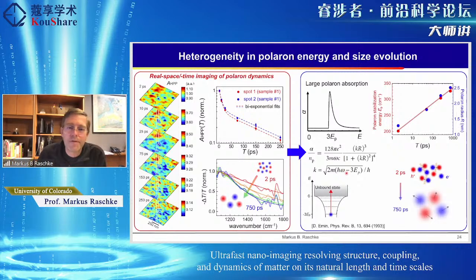And so there are two key parameters as these polarons annihilate each other, and that means that the remaining fewer polarons can polarize a larger local lattice environment. So one can think that there are more phonons increasingly available than for fewer polarons. These polarons grow, and as they do so, they increasingly become more stable. And this is captured in this model, which has two free parameters. One is this polaron radius, the size over which the electron polarizes the lattice, and the other is this polaron stabilization energy, so the depth of this potential. And then from fitting this model to these data, we can extract this evolution of this polaron stabilization energy correlating with this polaron radius. And so these polarons grow over time.